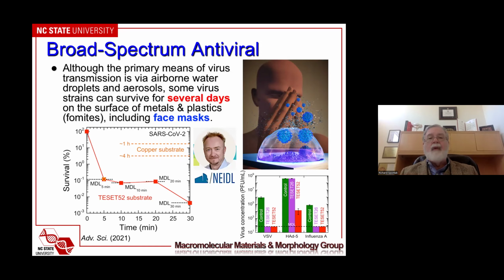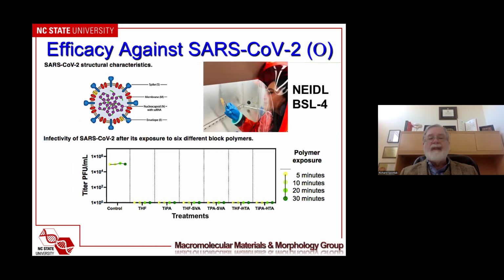They have a BSL-4 facility, and so we were able to test SARS-CoV-2 there and found that our polymer was far more effective by at least an order of magnitude compared to copper. In fact, here are the results from copper that were published in the New England Journal of Medicine, and you can see that even after 4 hours of exposure, the results are nowhere near what we could get in 5 minutes.